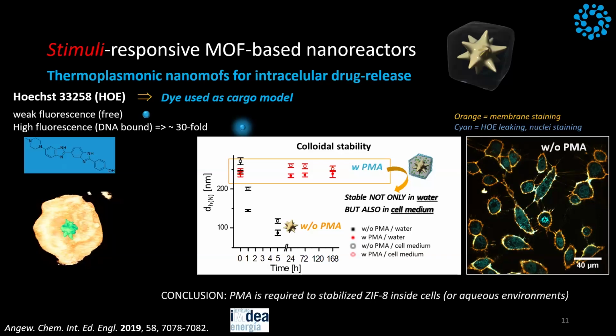So for us, initially, it was a reporter to know if we had leakage of the dye. So imagine you have the MOF, you put it to the cells, and then suddenly you have a lot of fluorescence in the dye. It's because the dye went out like crazy. That is what happened. Okay. So I was very naive at that point, and it happened that what is in all the papers is not true. So basically, ZIF-8, as long as you put it in water, it is destroyed. It is destroyed. So it takes seconds to be destroyed.